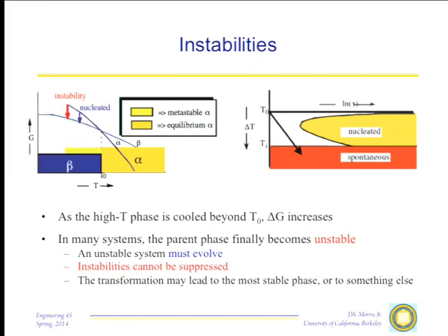The second thing to remember is that when we have an instability, for profound thermodynamic reasons, we always go unstable with respect to one variable, never to multiple variables. So if we have a transformation in which we change hypothetically the structure, the composition, and the state of order, for example, precipitating an ordered precipitate out of a solid solution, if we drive that by an instability, we will change only one of those, the composition, or the structure, or the state of order, never all three.